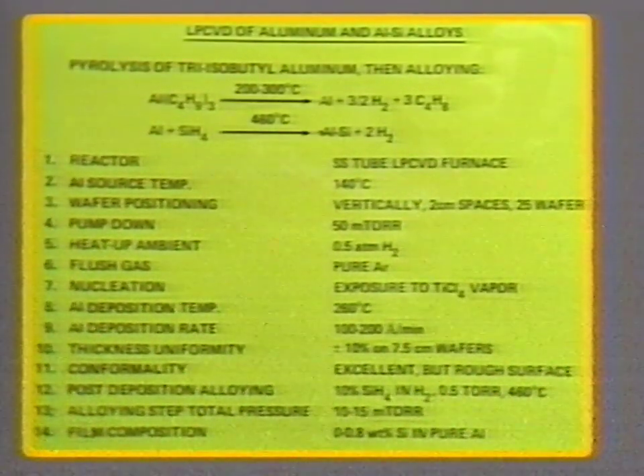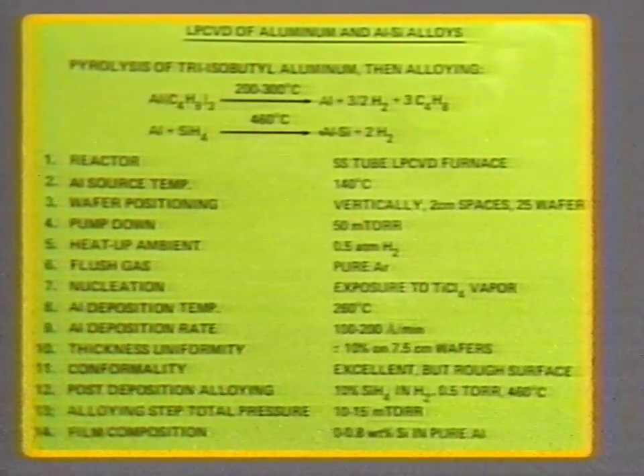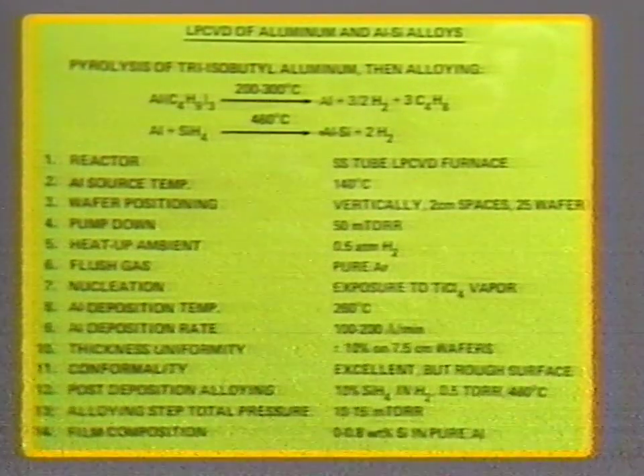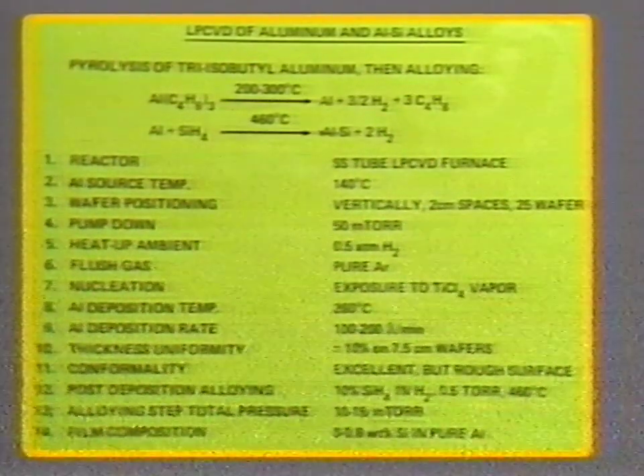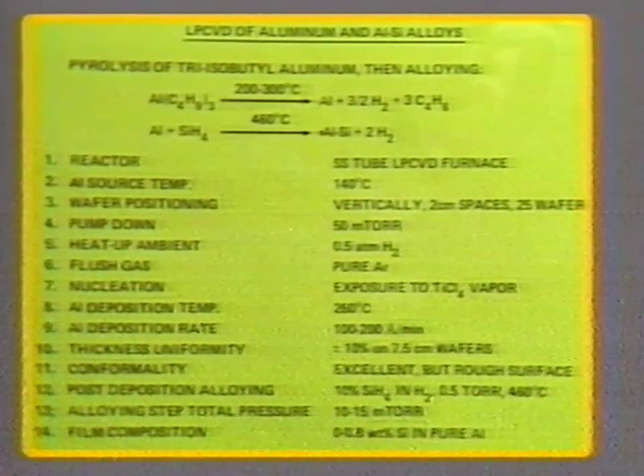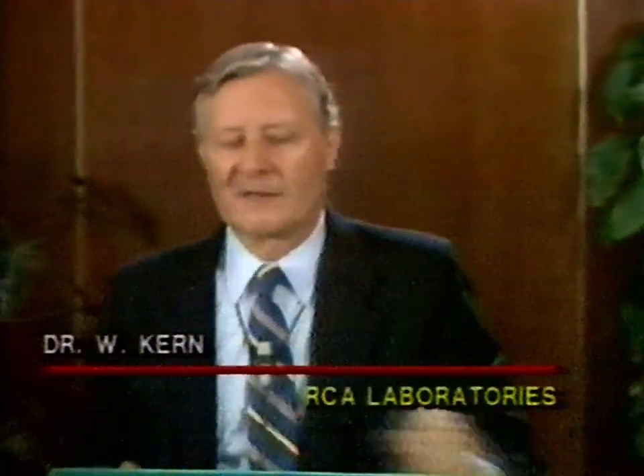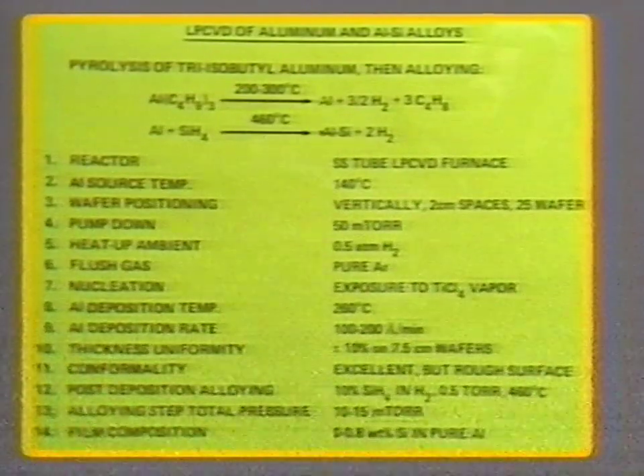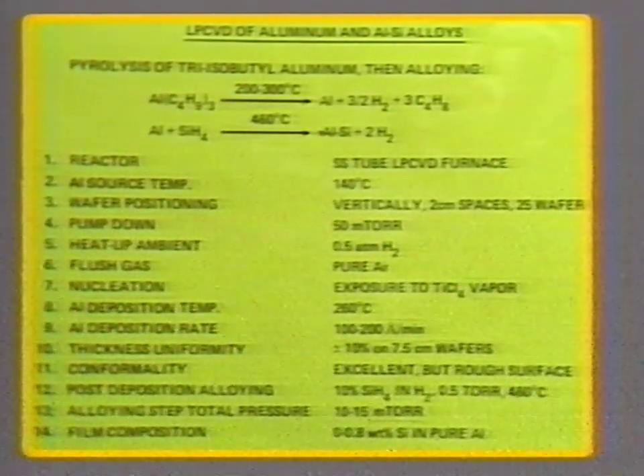Perhaps the most interesting aspect is the nucleation here. We do have to introduce some species of reactive material that nucleates the films. In this case, we use titanium tetrachloride that is introduced into the system and passed over the substrate and now forms nuclei from which aluminum growth takes place. If we don't do that, we get island formation and we get very irregular growth of aluminum. So this type of exposure now ensures a uniform nucleation. Now the aluminum deposition temperature is typically 260 degrees centigrade at the rate of 100 to 200 angstroms per minute.